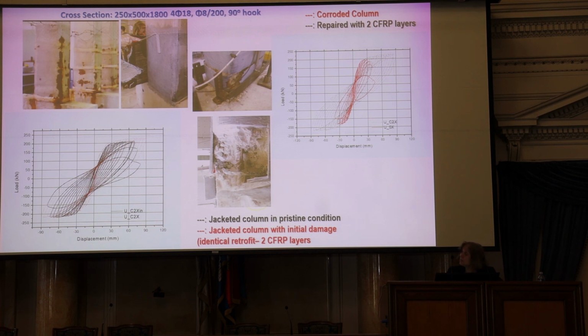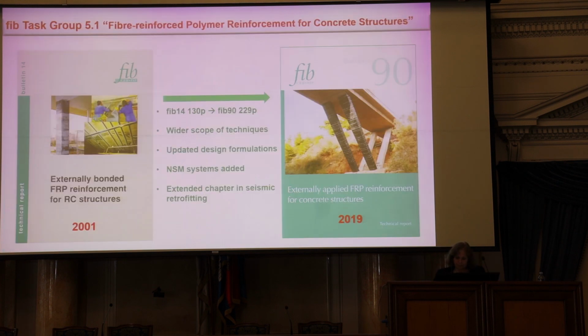All right, and similar experiments were conducted on larger scale columns. Again, the figure at the bottom shows you in a very fine red line the behavior of a jacketed column, identical to the one shown in black, but the one shown in black was not corroded. The one shown in red was corroded significantly and then jacketed with two CFRP layers, and of course the response under cyclic load was significantly improved.